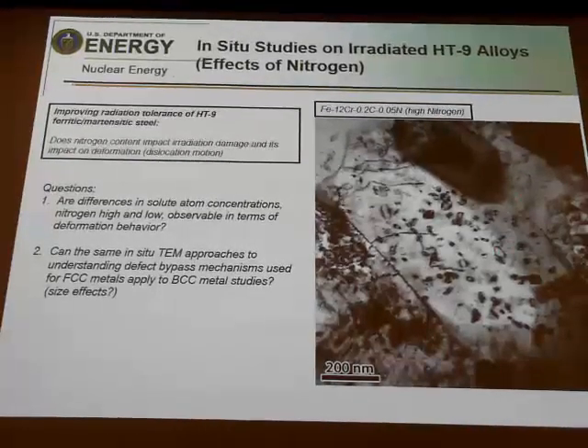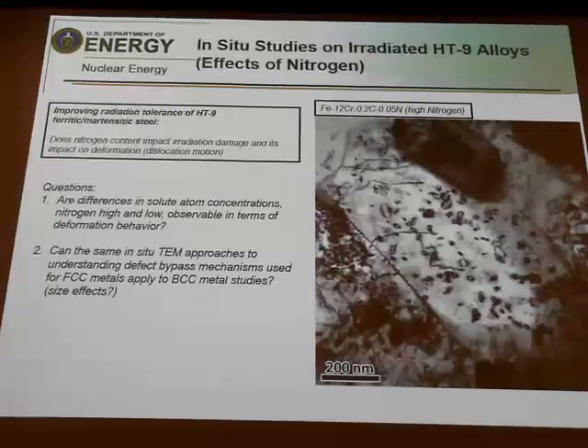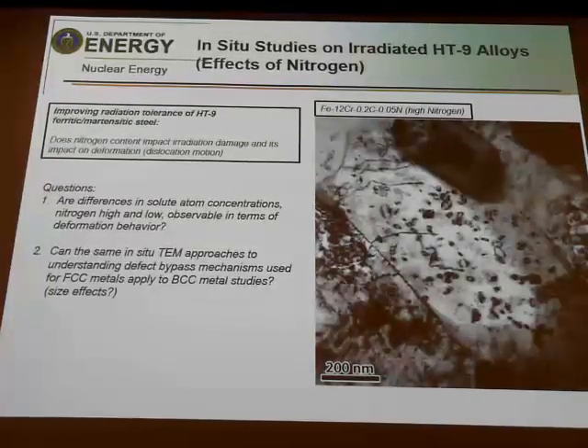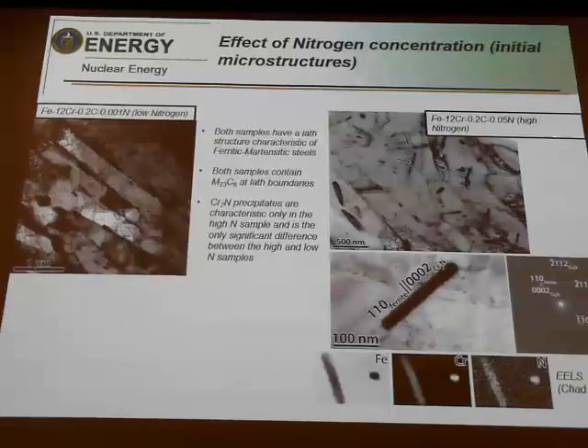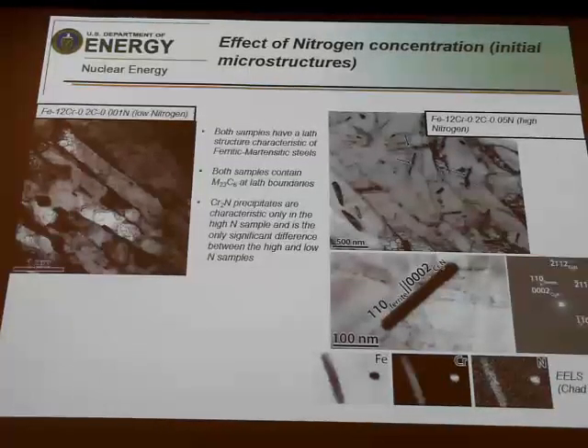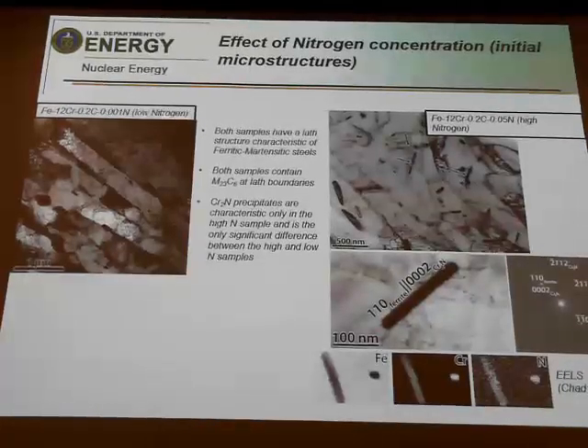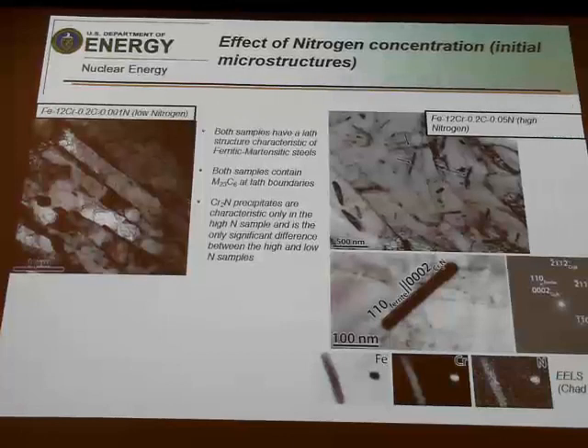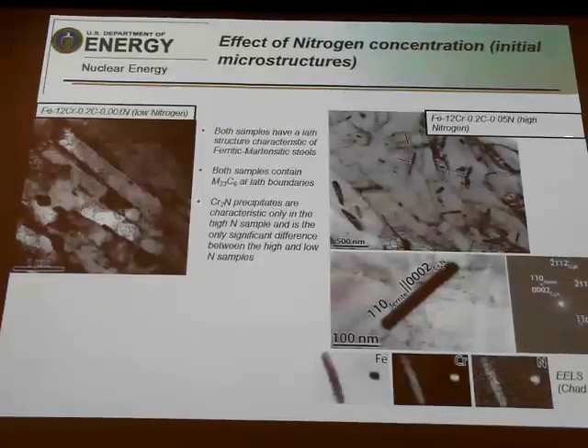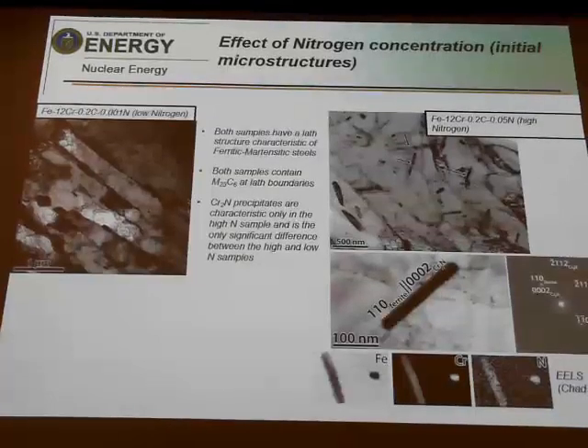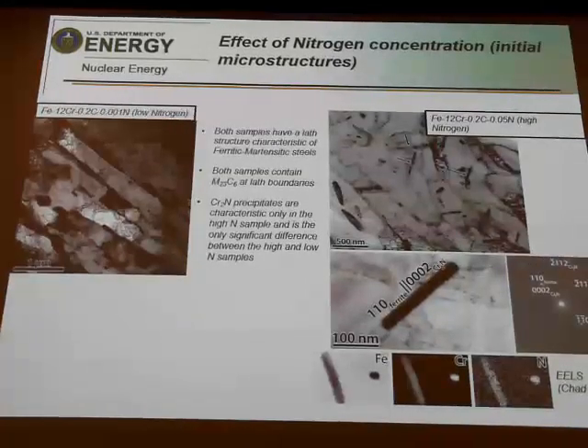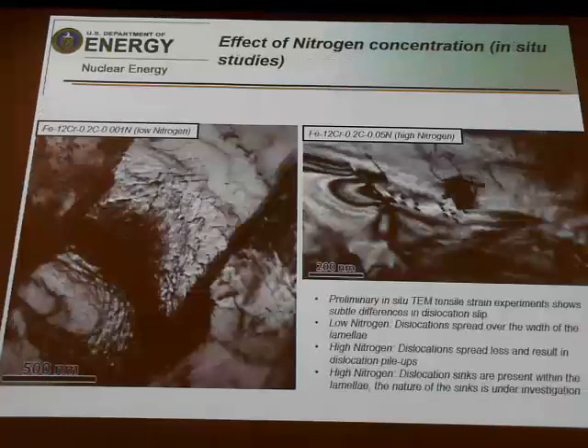And this is just some radiation damage microstructure in a high nitrogen alloy that you can see here. You can see that nitrogen doesn't really affect the lath structure of the material, but what it does affect is that we did have enough nitrogen that we're precipitating out some nitrides in the material. These are these chrome nitrides in the high nitrogen material on the right. And you don't see, of course, that in the 0.001 weight percent nitrogen low nitrogen alloy. So we know we maintain the lath structure, but we have a significant difference in nitrogen content in the material.